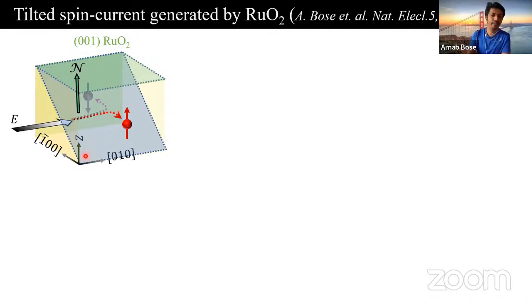The theory suggests that if we run current along the 010 direction, then we have spin current flowing in the 100 direction, as shown here, with spins being parallel to the Néel vector, meaning the 001 direction. Now you may wonder, this also happens in the regular spin Hall effect.